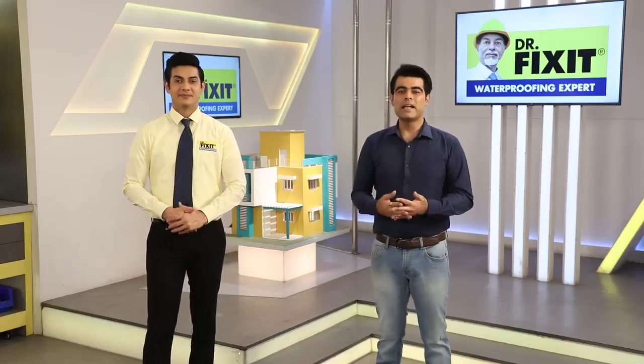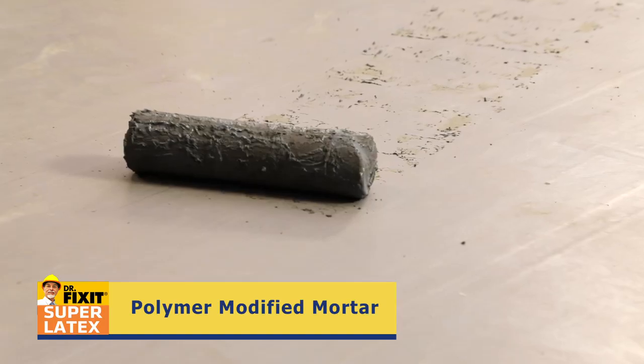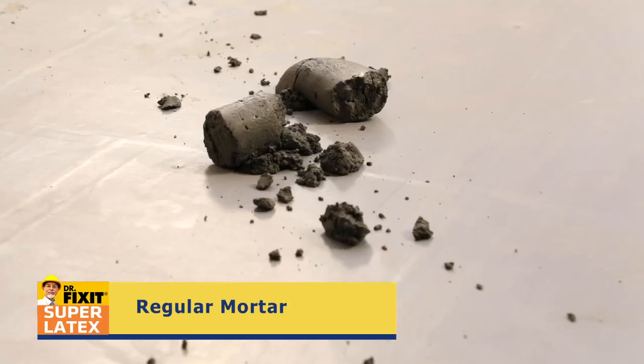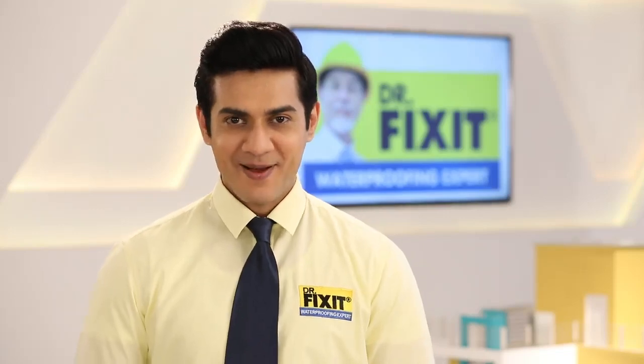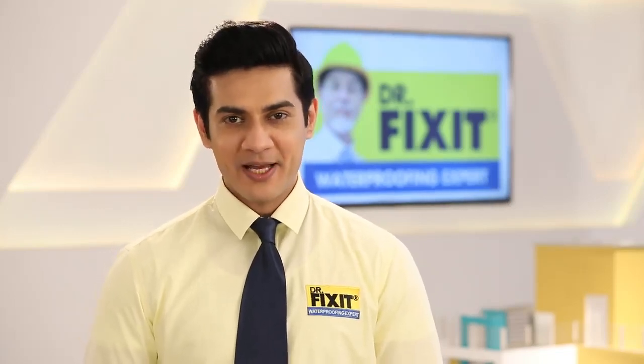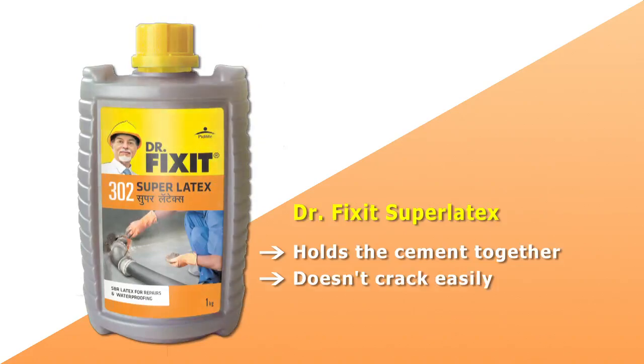Wow! The cylinder made from polymer mortar is completely intact, while the cylinder made from regular mortar is cracked into pieces very easily. So as I said, polymer modified mortar made with Dr. Fixit Super Latex holds the cement together and does not break or crack easily.